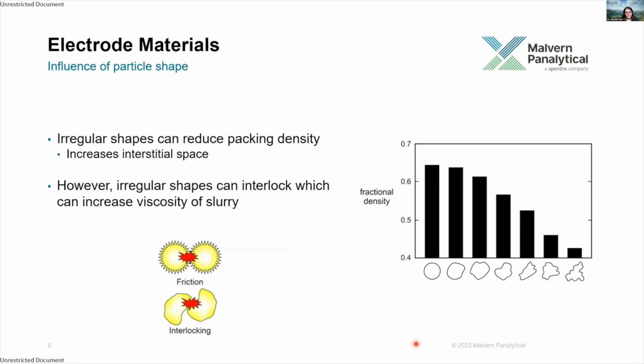So we've talked a lot about size, but particle shape is also important. Going back to packing density, irregularly shaped particles can reduce the packing density, which will increase the interstitial space for the electrolyte between the particles, which increases the ion transfer rate. However, irregular shapes can cause particle friction and interlocking, which can increase the viscosity of the slurry, which impacts its application. Generally, more spherical particle morphologies are preferred due to their ease of packing.